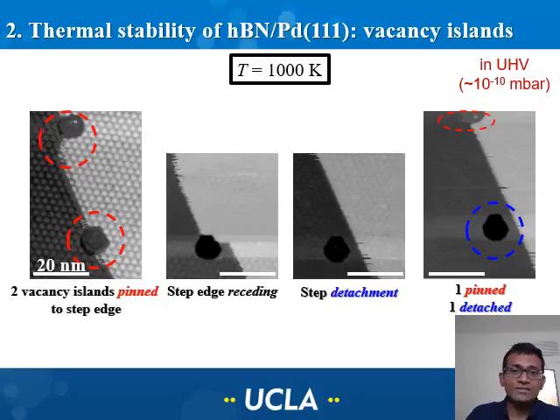Another interesting aspect that we observe is these vacancy islands that are in palladium but under the boron nitride layer. As the step edge moves, they detach from the step edges and form their own isolated islands.